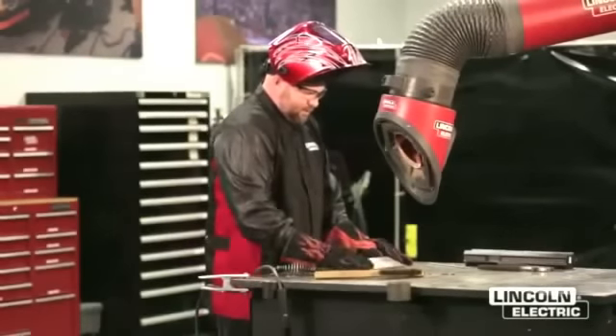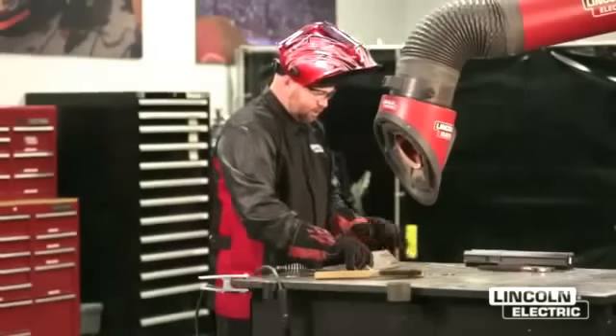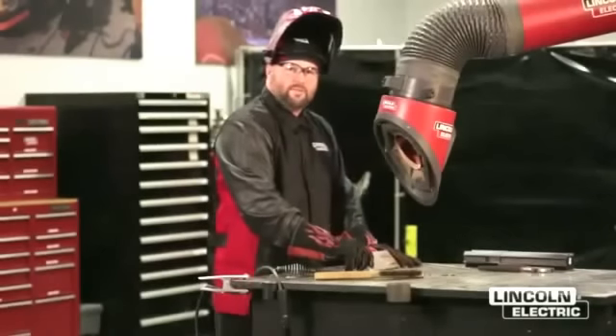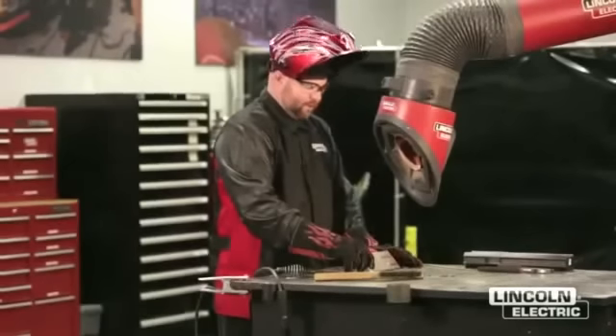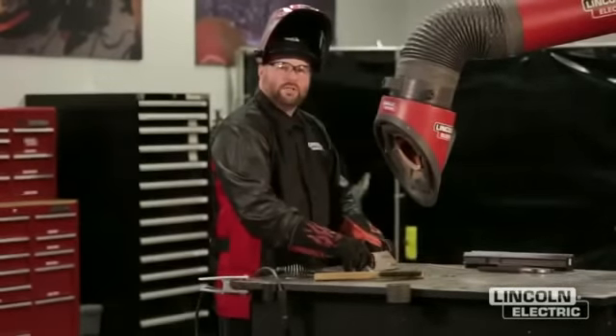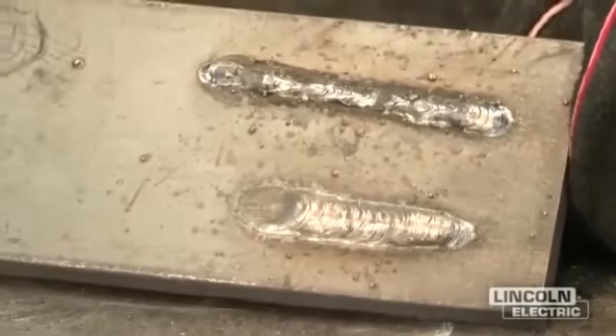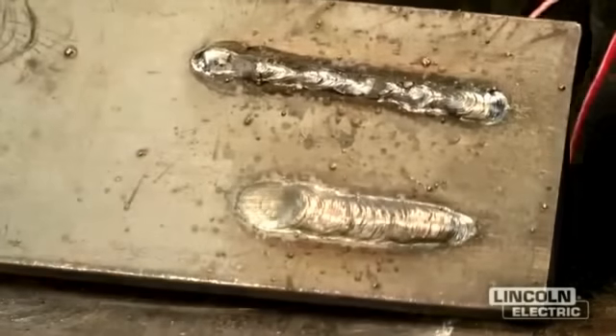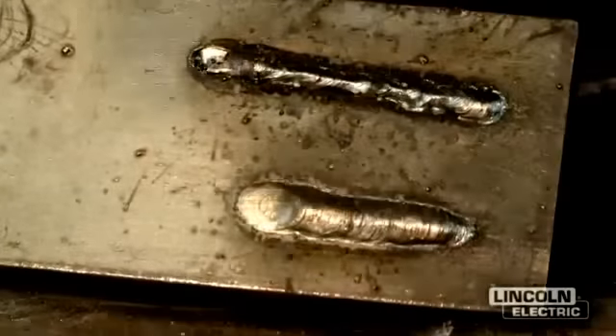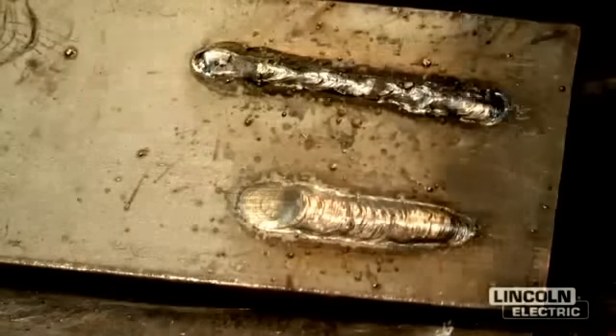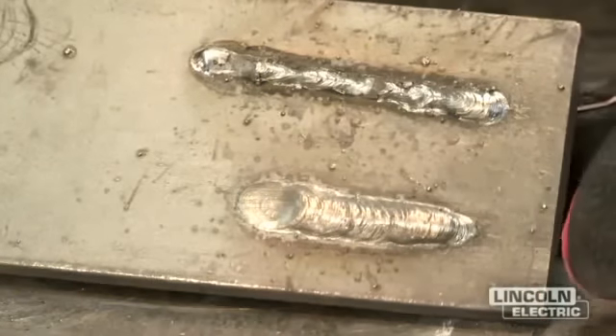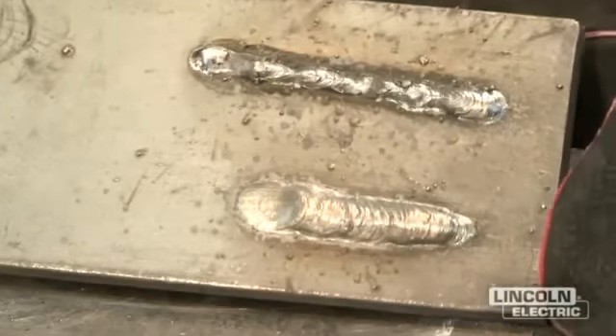So we just made a weld with that 1/8 6013 electrode. The same setting as we made the first one, too fast with travel speed, 135 amps, but now you'll notice how skinny that weld is and we were actually outrunning the weld puddle. So that's telling us that we need to slow down just a little bit and we'll achieve the appearance that we're looking for, a proper weld.